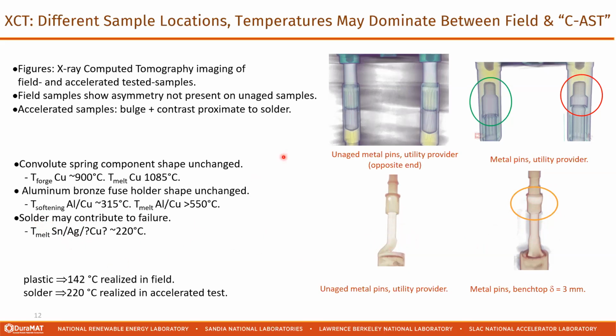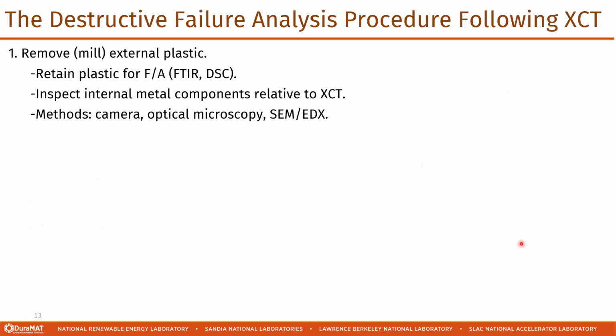And so certainly in both of these samples with a history, we're getting hot enough to melt the plastic, the polycarbonate, but potentially we're getting hotter than that in the accelerated test. So now let's step back and talk about the destructive failure analysis, after the XCT, I should say.